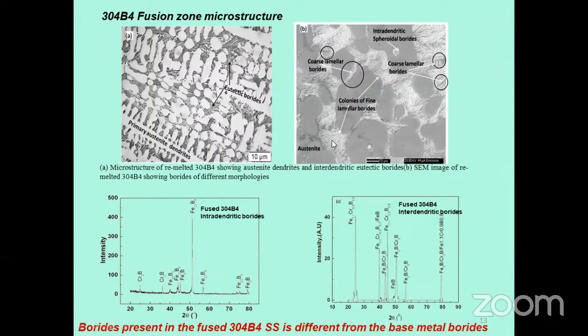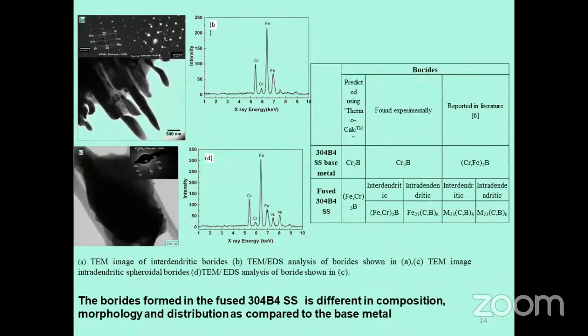We again extracted these borides from the fusion zone and characterized them. We could see that they are not only chromium borides, Cr2B type, but of different stoichiometry. We analyzed this through XRD. We can see M23B6, Fe23B6 type borides are formed, and FeB and Fe2B type borides are formed, in addition to Cr2B type borides. We have different stoichiometries and different varieties of borides in the fusion zone. We also confirmed all these different borides using TEM.